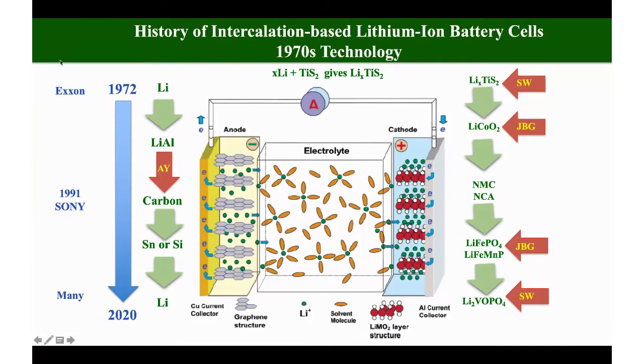So we started in 1972, '73, and this is Exxon. We used lithium metal as the anode. We used titanium disulfide as the cathode, and this is a layer structure as shown on the right-hand side here. And all you're doing is moving lithium ions in and out of the structure without changing that structure. And that's what we mean by intercalation. So you intercalate an ion into a structure, just like you intercalate February 29th into the calendar every 4th year. So it's a totally reversible reaction.